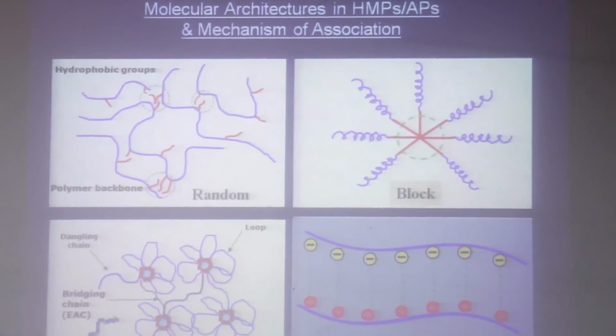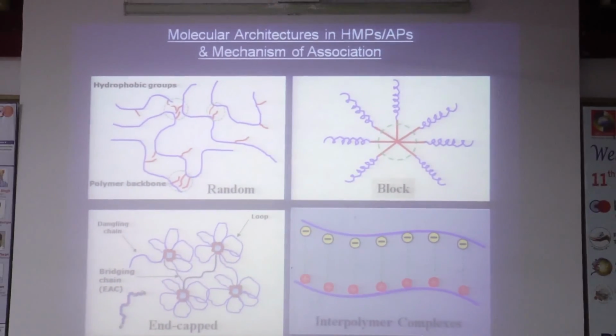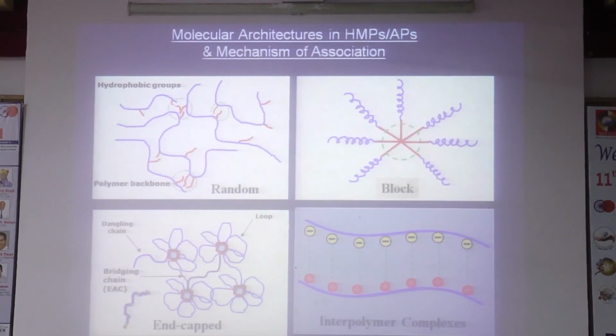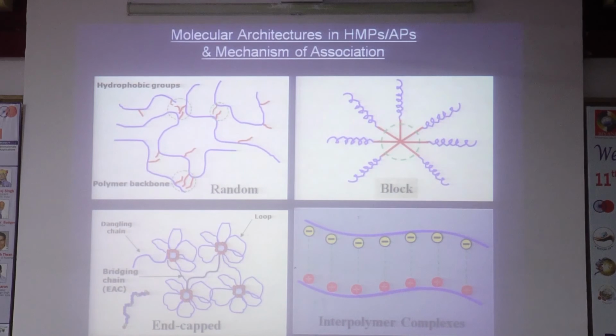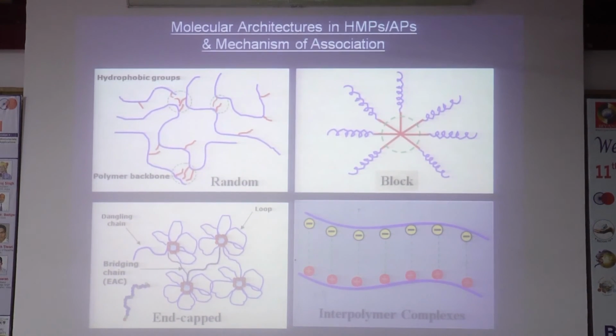So it is like this. This is a hydrophilic polymer, you put hydrophobic at the end of the polymer, and when you take this polymer and put it in water, the hydrophobic compounds come closer together and they make flower-like micelles like this, and these flower-like micelles bridge, and then they increase the viscosity of the polymer solution. So this is called end capping of the polymers, and this gives a very interesting property of increasing the viscosity of creams, lotions, and some of the inks and all. So these are the modular structures one can put in.